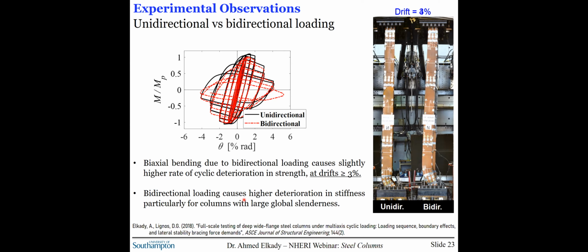We also observed larger rates of cyclic deterioration, specifically at drifts larger than 3%, when we are looking at columns subjected to unidirectional and bidirectional loading. So by looking at this comparison, you will see that essentially under bidirectional loading or biaxial bending, there is a higher rate of deterioration in the strength, especially when you go to large drifts. At the same time, because you are pushing at the top out of plane, you are getting additional weak axis bending, and you are getting larger out of plane deformations, and eventually you are getting higher deterioration in stiffness.